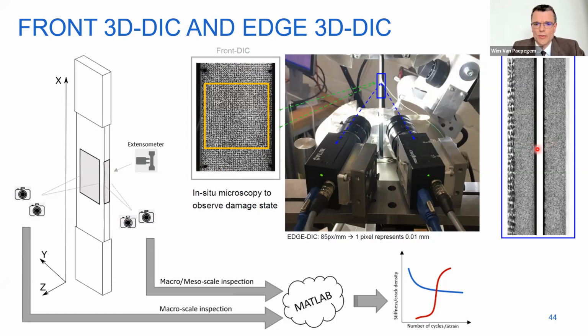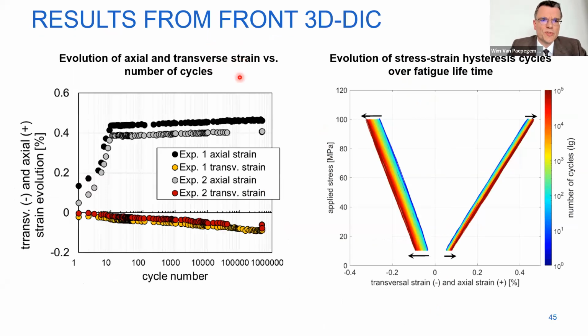And what can we get out of these measurements? First of all, I will show you the front DIC. This is still, let's say, more standard. And I will show it to you in fatigue. The reason why I show it in fatigue and not in a static loading is to show you also a bit the power of this method, because in fatigue you can really extract a lot of data from this. So here you have 2 experiments, experiment 1 and 2, where for both of them I show you the longitudinal or axial strain, and the transverse strain.